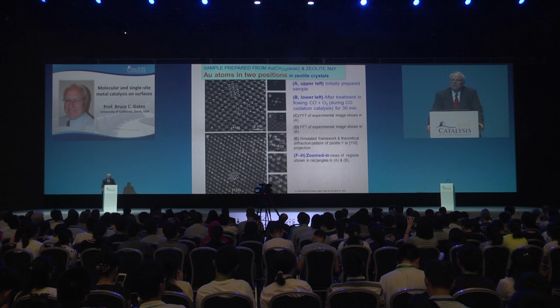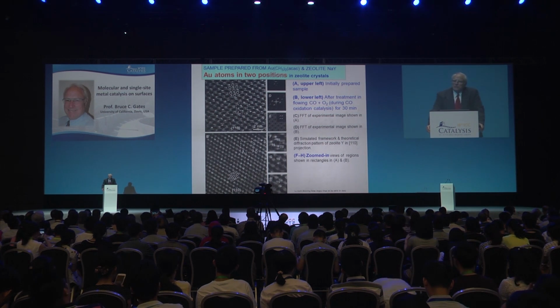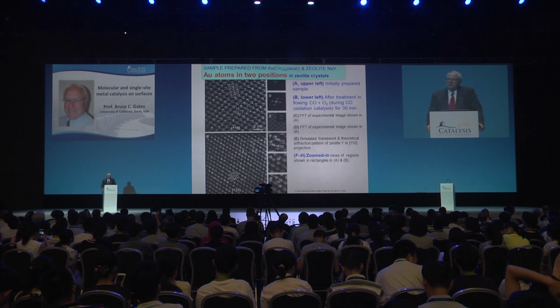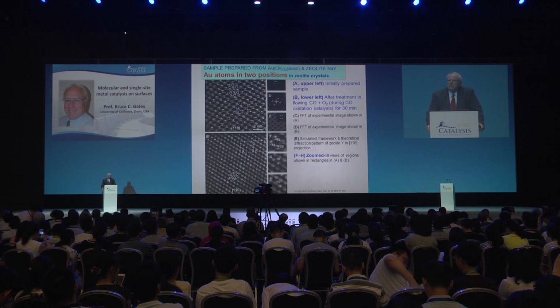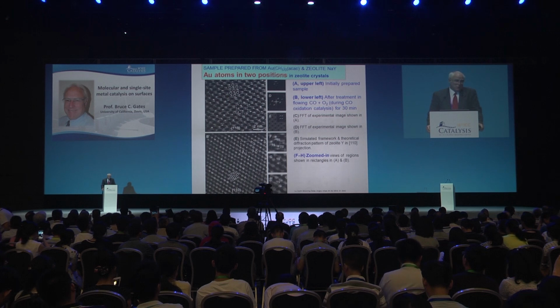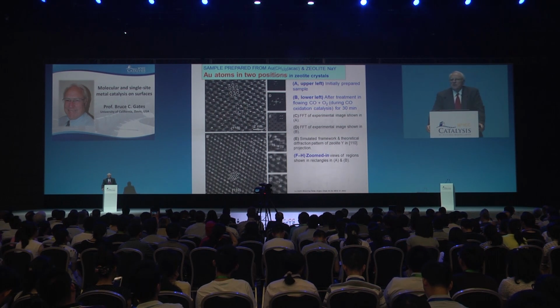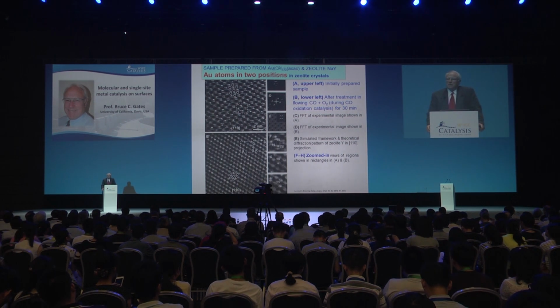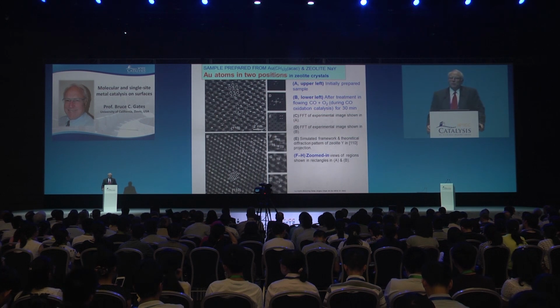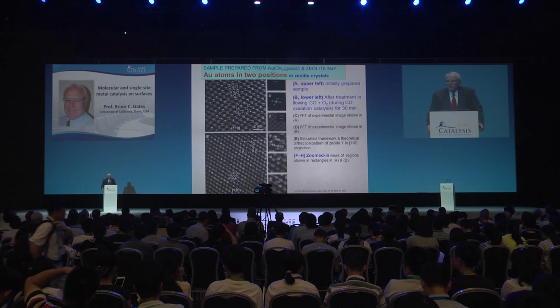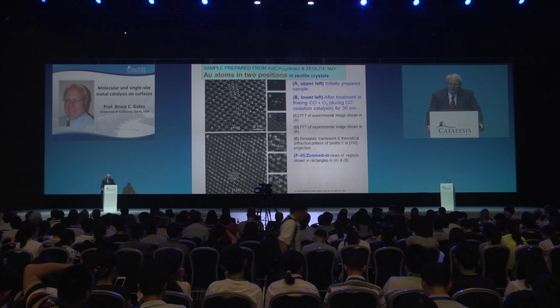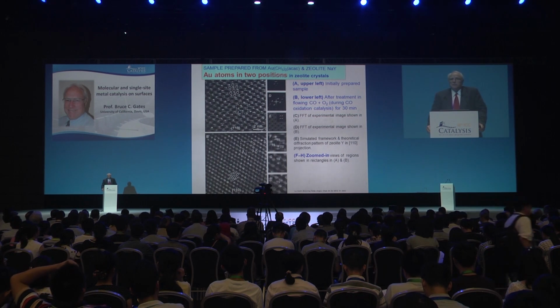As we initially make the sample, we have a distribution of the gold between those two sites. After we use it as a catalyst, low temperature catalyst, it's not very stable, for CO oxidation, the distribution of the gold between the two sites changes. So there's chemistry going on. The gold's oxidation state is changing during that as well.